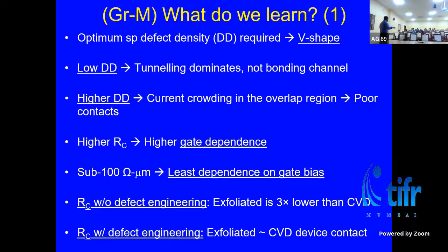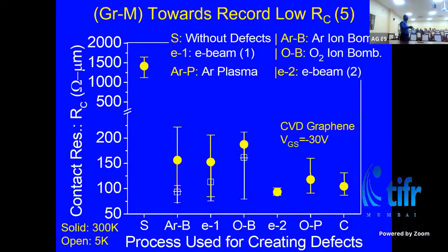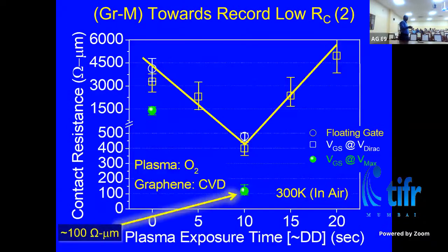When you have high defect density, the contact resistance increases because of the current crowding in the contact region. What I did not talk about was that when you have high contact resistance, there is a big difference depending on the gate bias. But I don't want my contact to be a function of the vertical gate field, or the gate field-based electrostatic doping in the contact area. I want the contact to be ideal and transparent, and it should behave the same no matter what the gate field is, right?